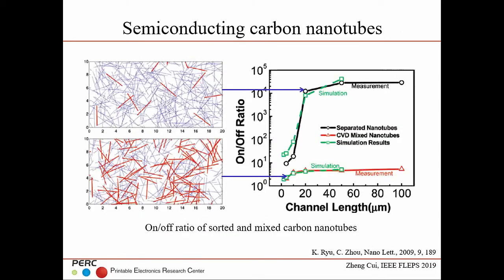Okay, let's look at the carbon nanotube first. We know the carbon nanotube is always a mixture of metallic and semiconducting tubes. If you use the carbon nanotube as synthesized, there are a lot of metallic tubes, as the red line indicates. When you make the transistor, you don't have a very high on-off ratio because all the metallic tubes become a conducting path. Then you cannot switch off effectively for these transistors. So we have to get rid of the metallic tubes and make it as pure as possible, only semiconducting tubes, so that you can make a good transistor.